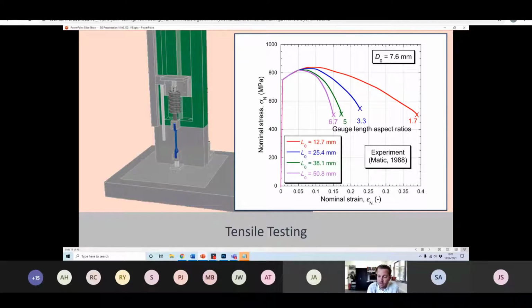Okay? And as one example, and we won't name names, we've worked in the past to help a company that were using ductility values, measured nominal strain at failure in their finite element calculations or crash simulations, not understanding that it's totally sensitive to the specimen dimensions they were using in their tensile tests, and it's made a big difference to the predicted outcomes from those FE simulations. So it's something that's not well understood, but it's something that's crucially important in some cases because, of course, it's related to fracture and failure.